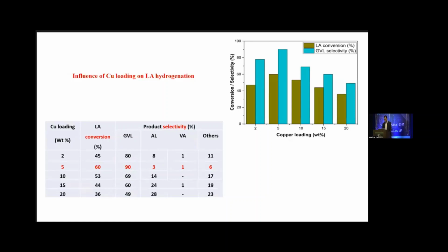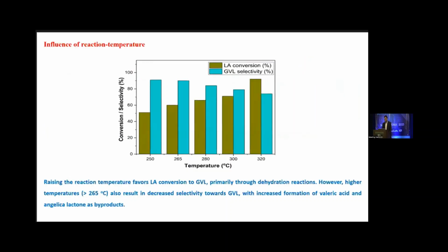So we explore the effect of loading of copper on levulinic acid hydrogenation, and it was found that 5 weight percent is the optimum weight percent that can lead to high selectivity, which reaches 90%, and conversion of 60% of levulinic acid to GVL. We also explore the effect of the temperature, and 265 is the optimum temperature for high selectivity and high conversion.